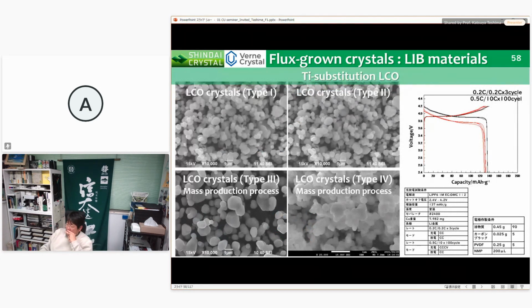We have fabricated a variety of substitutional cathode materials to improve LIB performances. These pictures show titanium-doped LCO materials. The addition of titanium allows uniform particles to be grown. Crystal particles of different sizes can also be produced by controlling the crystal growth conditions, like these pictures.